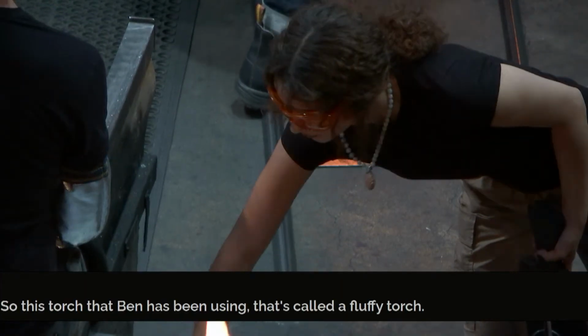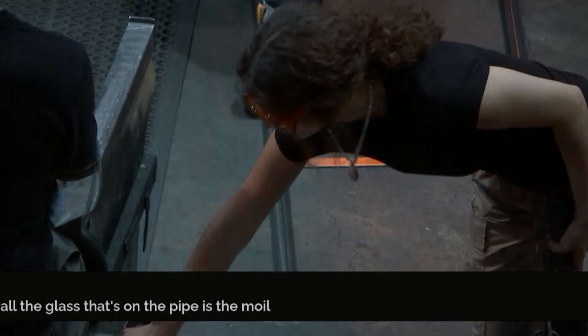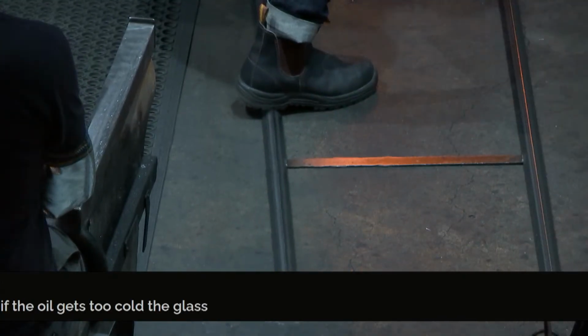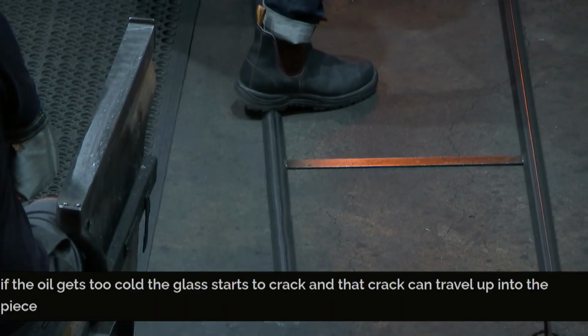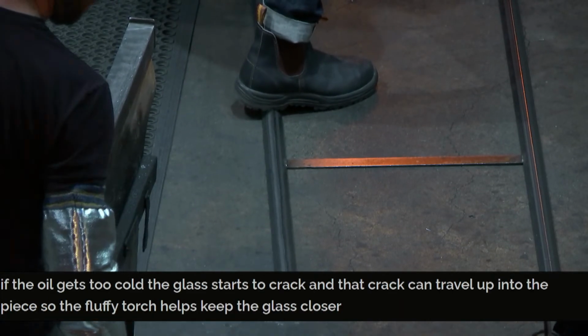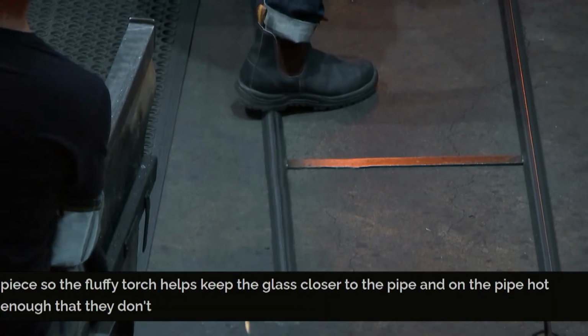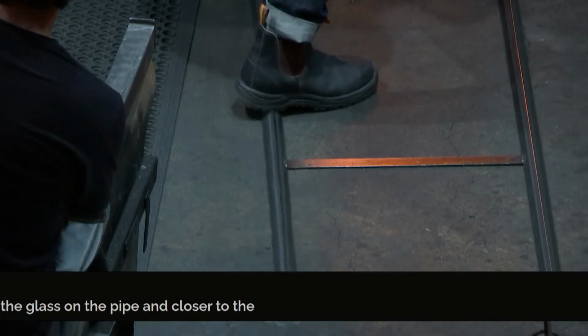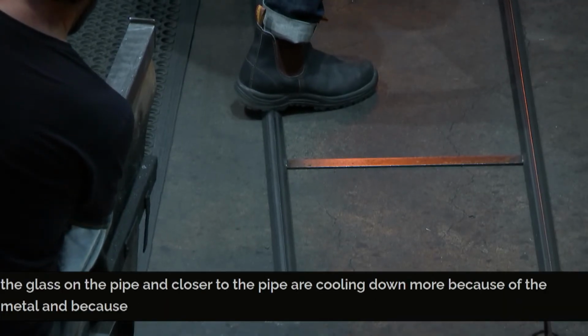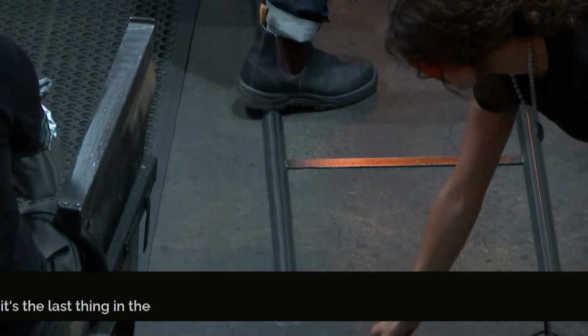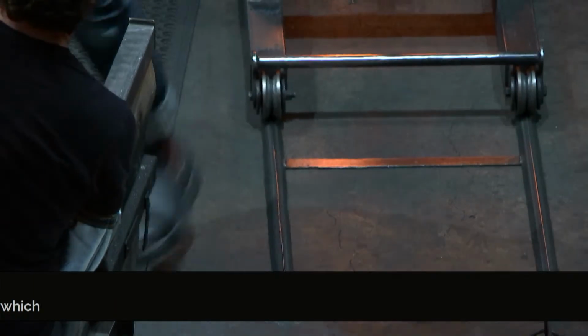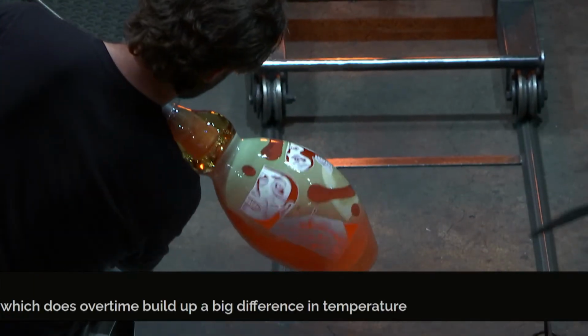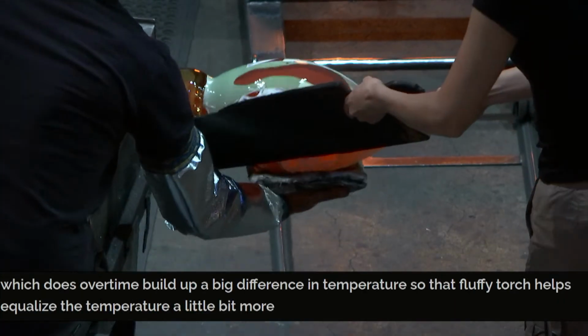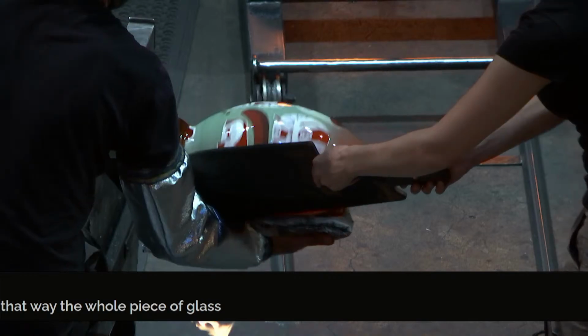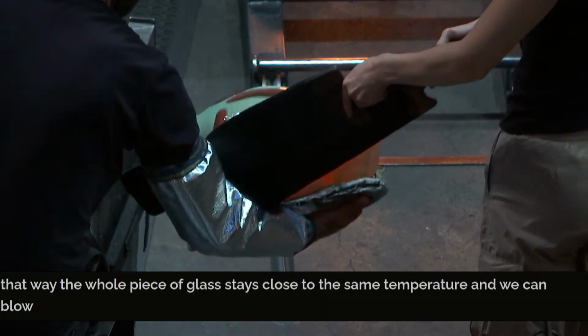So this torch that Ben has been using, that's called a fluffy torch. All the glass that's on the pipe is the moil. If the moil gets too cold, the glass starts to crack, and that crack can travel up into the piece. So the fluffy torch helps keep the glass closer to the pipe hot enough that they don't crack. The glass on the pipe and closer to the pipe is cooling down more because of the metal and because it's the last thing in the fire and the first thing out, which does, over time, build up a big difference in temperature. So that fluffy torch helps equalize the temperature a little bit more. That way, the whole piece of glass stays close to the same temperature, and we can blow out the glass and it expands evenly.